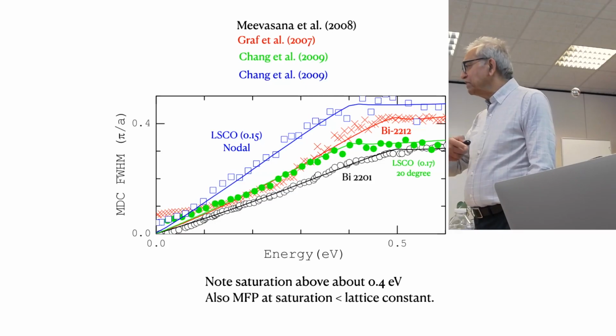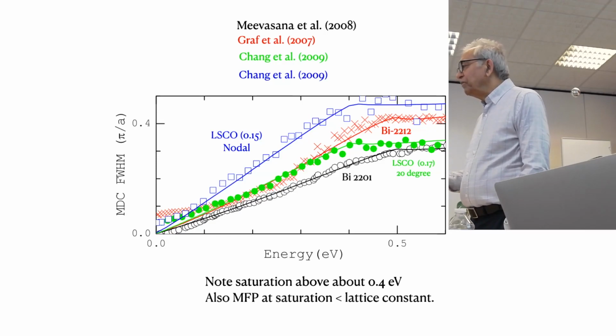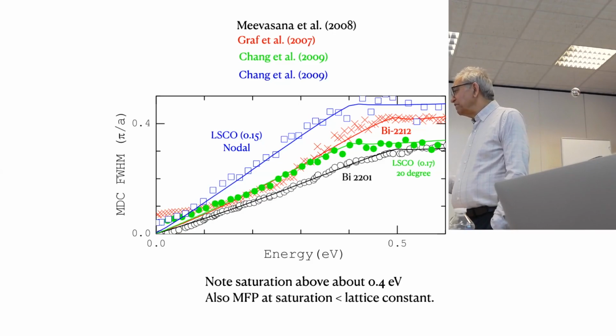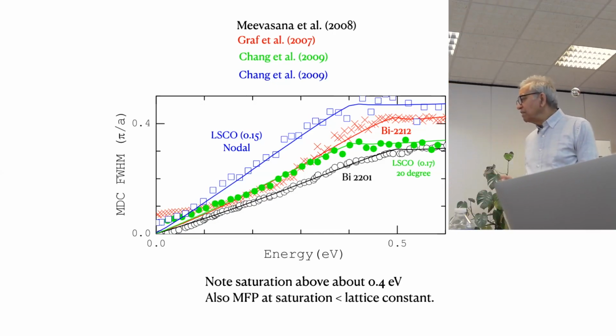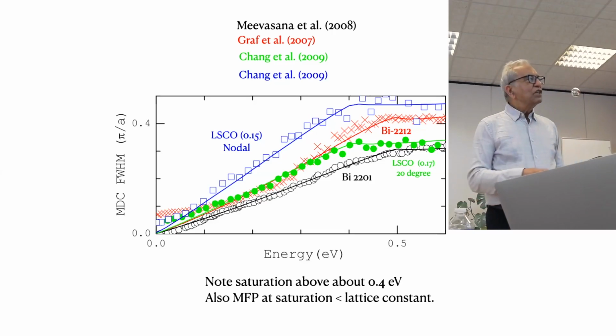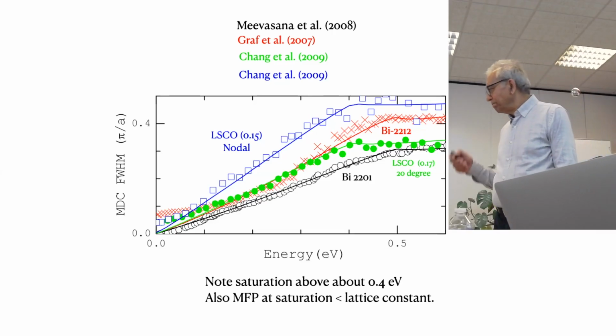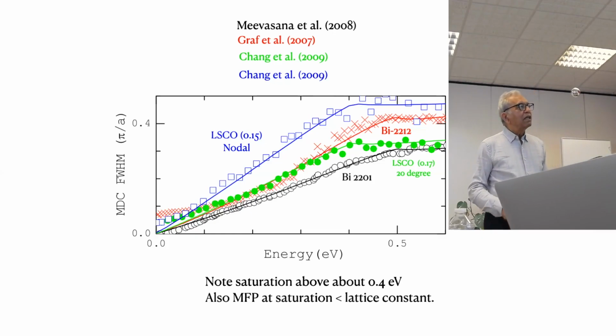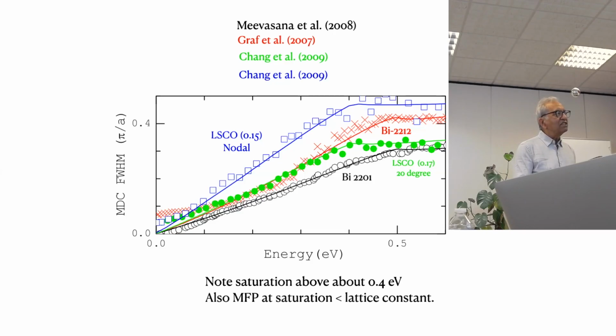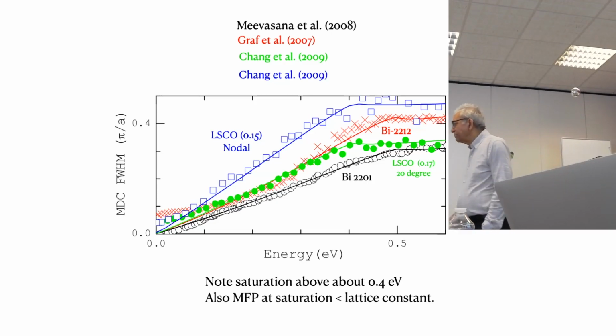So to a first approximation, the scattering rate is independent of the angle, and in fact you can relate it purely to the fact that the Fermi velocity in the antinodal direction is smaller, the density is higher than the nodal direction, and if you extrapolate that for a circular Fermi surface, one would say it's likely to be the same. Okay, so what I can tell you is that given these 2 parameters, Chandra, just to understand this, the LSCO is in the nodal direction, and then the angle is varying? There are 2: LSCO 0.15 in the nodal direction, and green is LSCO at 20 degrees at 0.17. Okay. And of course, it's above Tc. Yeah, both are above Tc. That's good.